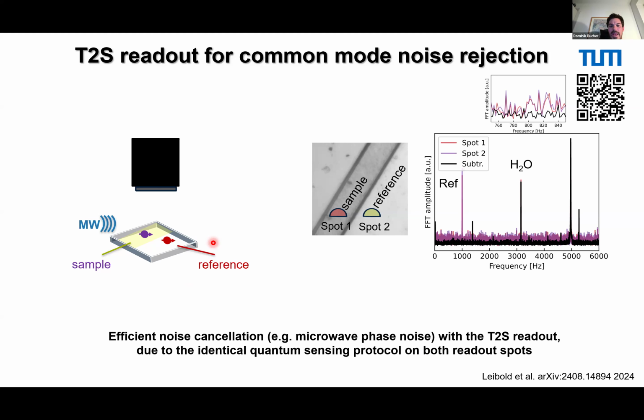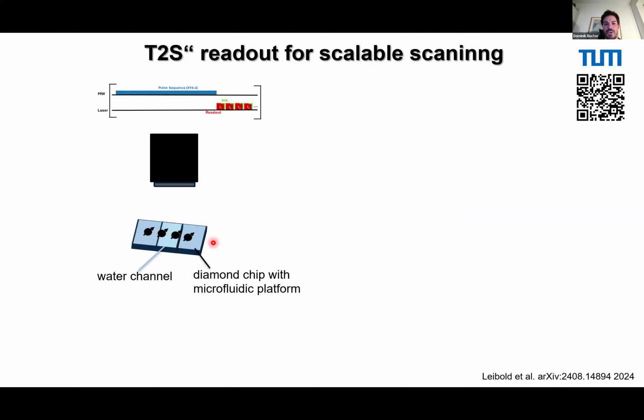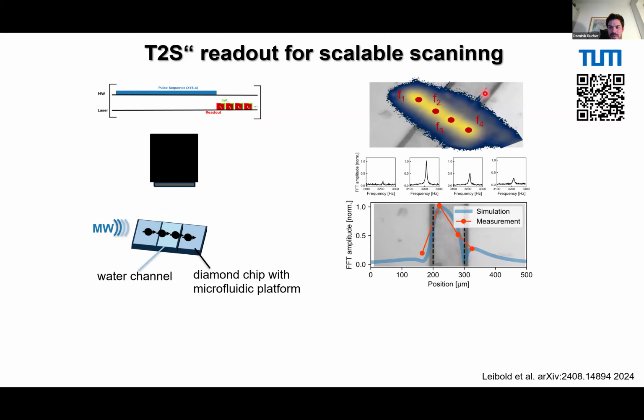The second one is for imaging. So what we would do here is you have a long pulse sequence. For example, if you measure T1, if you think about nanodiamonds, you measure T1 times, so you have a very long pulse sequence, and then you read out for 5 microseconds, and you have to start again. So what we can do now, it's shown here in the case of NMR, but again, I think especially for T1 measurements, this might be very beneficial. You would apply your pulse sequence on all the spins. You have a long measurement sequence of milliseconds, and then you read out all the spins very quickly one after each other. And we've seen this here, we just do the NMR with 4 spots. You can do this with many more spots, and we can do primitive imaging here.